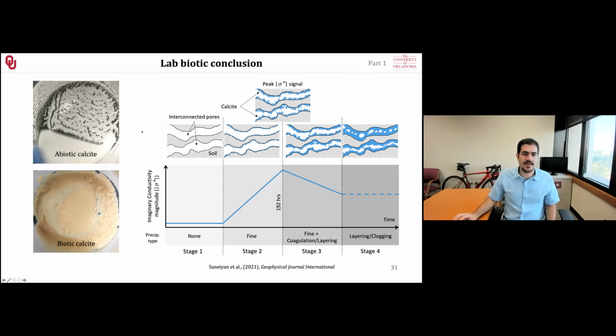Just to emphasize that the microbes produced a more homogeneous distribution compared to abiotic calcite precipitation, we replicated everything at the bottom of a beaker, and we clearly see that using only chemicals for this precipitation, everything starts to coagulate initially, and we see empty spots. This is not a good distribution of calcite precipitation at the bottom of a beaker. This is exactly the same thing that is happening inside our soil if we're doing this in the field or in our column in the lab.